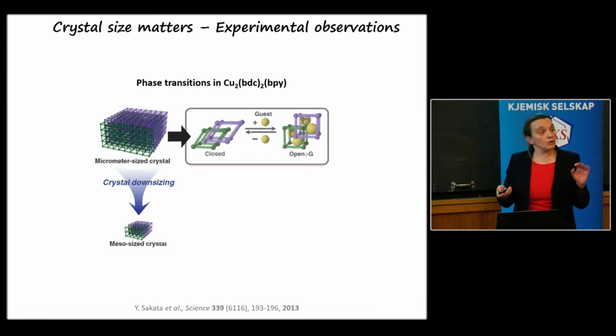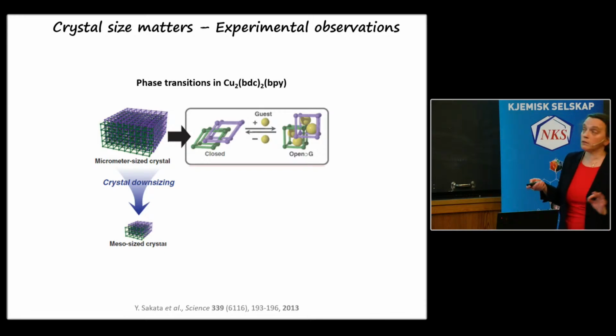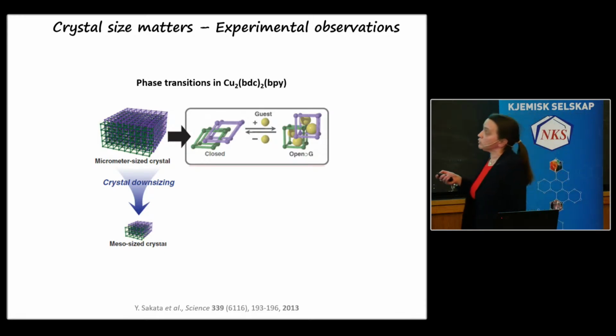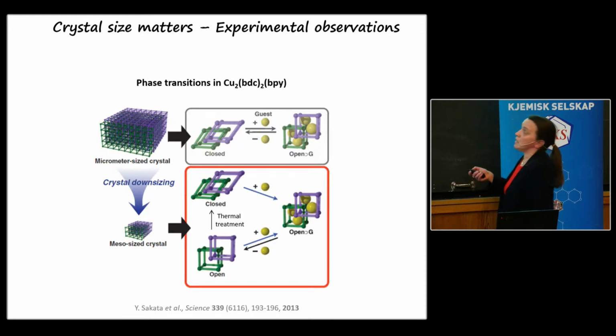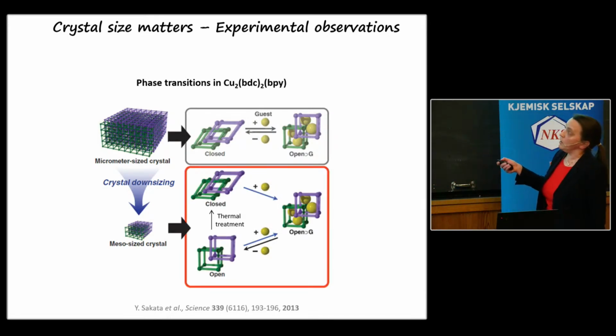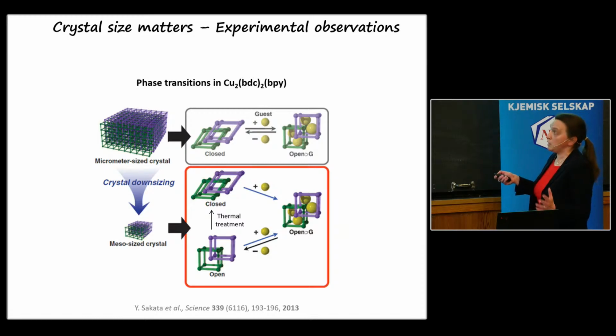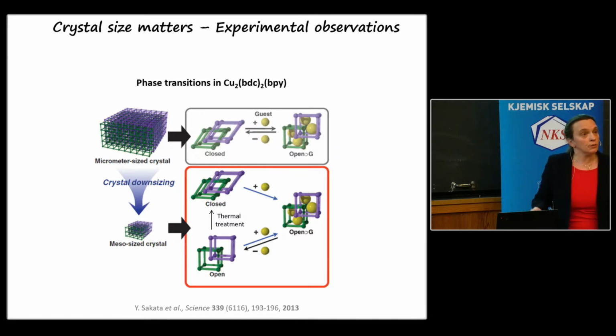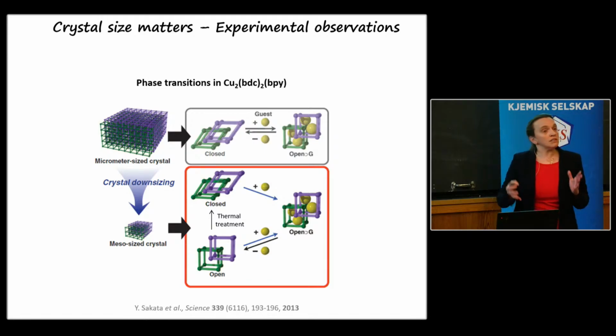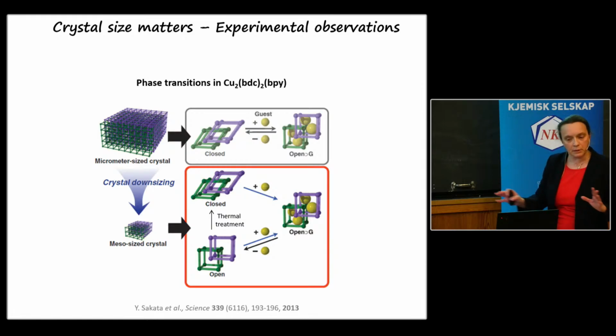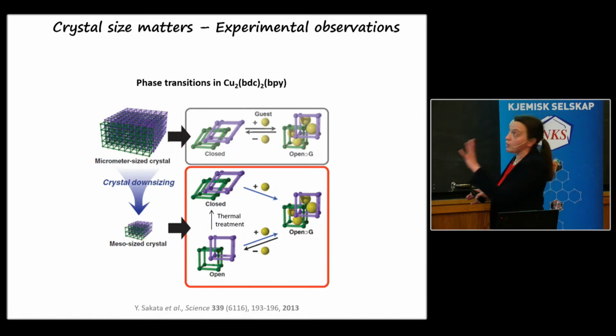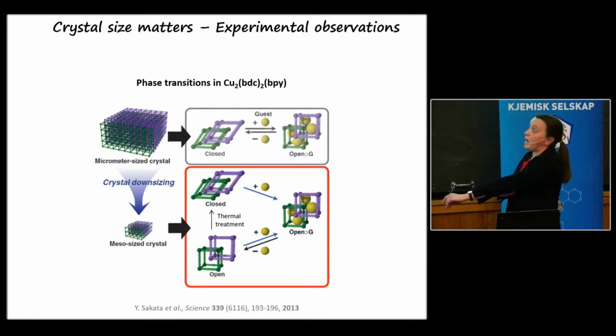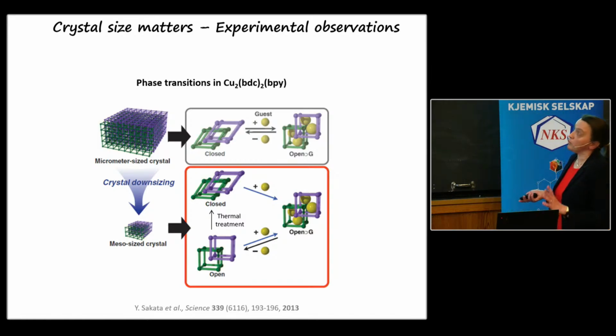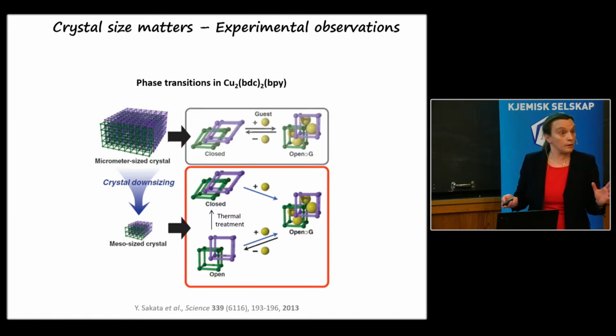Now we are going to downsize the material to meso-sized crystals. What do we see? We start from the closed pore phase. Gas molecules enter, the material opens, and then we remove the gas again, but the material stays open. So it's not reversible anymore. So this behavior is critically dependent on the crystal size. This was one of the earliest reports, but by now, there are many other reports that have seen similar things.